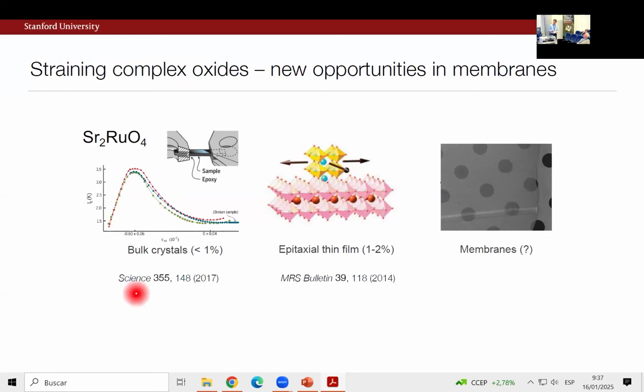If I remember correctly, Jacobo might have even shown the exact same picture, but many of us in this room that are utilizing epitaxial strain in thin films confront and use this all the time. That is to say, by providing an epitaxial template, you can stretch and strain a material in a thin regime where it's complying to the substrate. These are rough numbers, but certainly on the room temperature scale, the fracture strain that people encounter is far less than 1%.